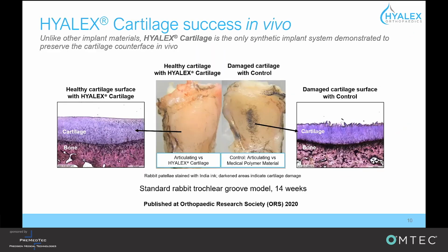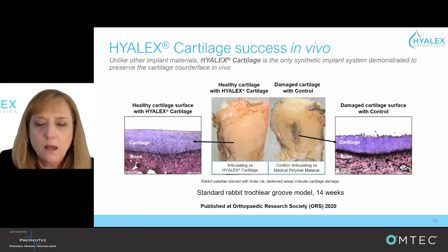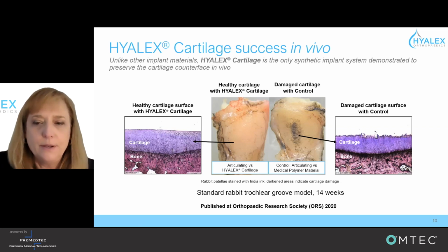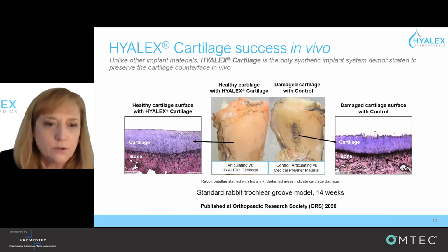The center left photo shows the surface of the patellar cartilage that articulated against the Hyalex cartilage. India ink staining was used to highlight any cartilage damage. You can see that the surface looks pristine with no damage visible. And this is also confirmed by the histology section on the left. In contrast, the center right photo shows the patellar cartilage after articulating against a control polymer. The staining highlights the damage onto the cartilage surface, which is also seen in the histology section on the right. Unlike traditional orthopedic implant materials, Hyalex cartilage, with its cartilage-like mechanical properties and its low coefficient of friction, can be used to repair cartilage lesions and preserve the opposing cartilage surface.